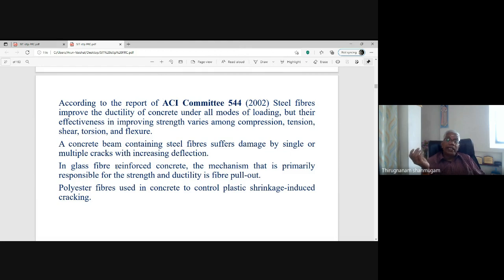A concrete beam containing steel fibers suffers damage by single or multiple cracks with increasing deflection. So this FRC beam suffers a multiple cracking mechanism as the deflection is increasing. In glass fiber reinforced concrete, the mechanism that is primarily responsible for the strength and ductility is fiber pullout. The glass fiber surface is smooth, so the failure mechanism is due to the fiber pullout.